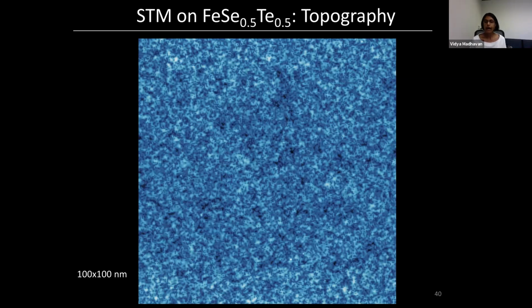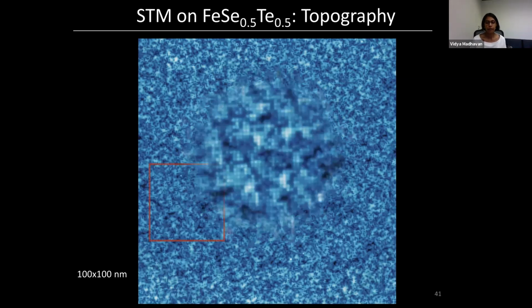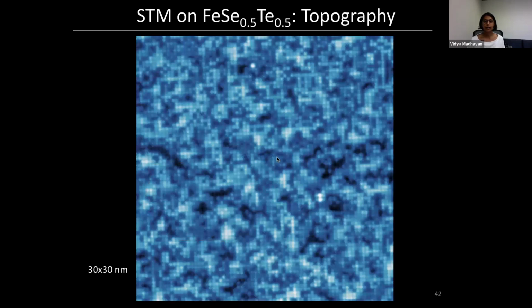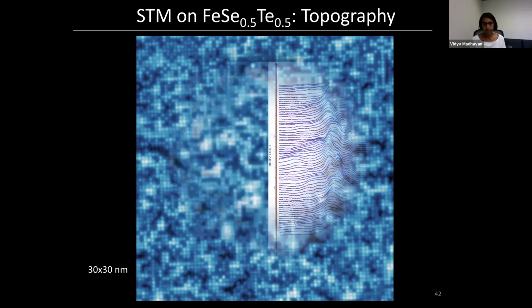Each dot is in fact an individual selenium or tellurium atom. And you can zoom in and you can see these are the selenium and tellurium atoms on the surface. The reason that this topography is so inhomogeneous, meaning that you have bright regions and dark regions, is that this is a 50-50 alloy of selenium and tellurium. And as it turns out, the seleniums and the telluriums are not equally bright in STM topography.